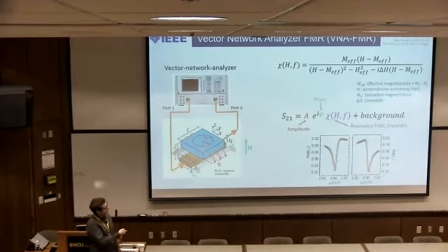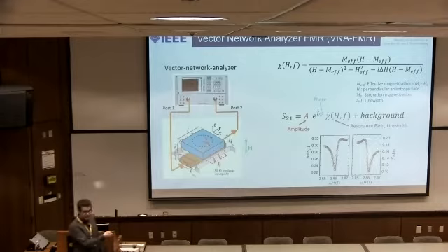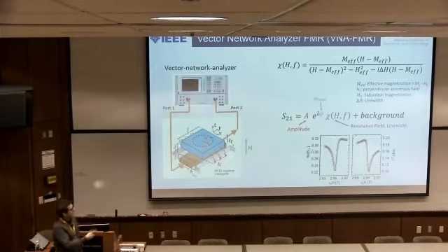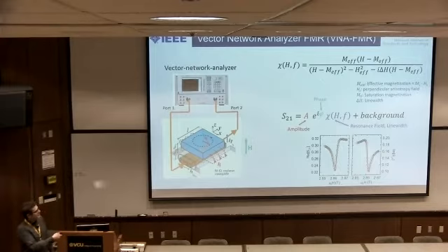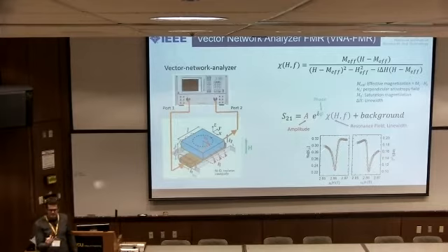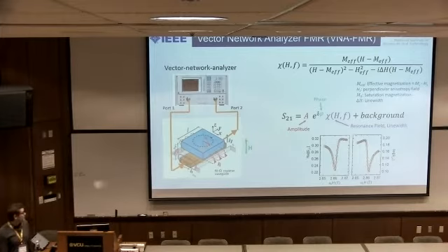So from this fit, we get 4 pieces of information. One is we get the resonance field, so that's the location of this peak. We get a line width, which is the width of that peak, obviously. We get an amplitude, which, as it says, is the strength of that peak. And then finally, we get a phase. And so that's the relationship between the real and imaginary part. And so this is the very important thing. We get these 4 parameters from this fit.